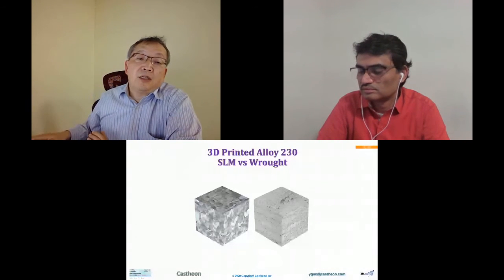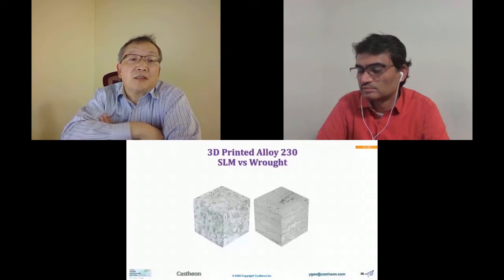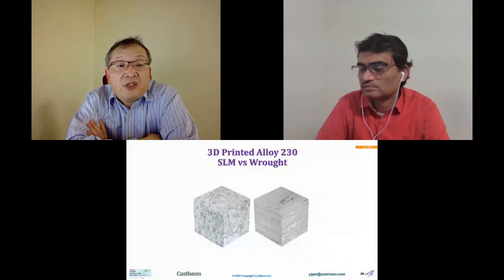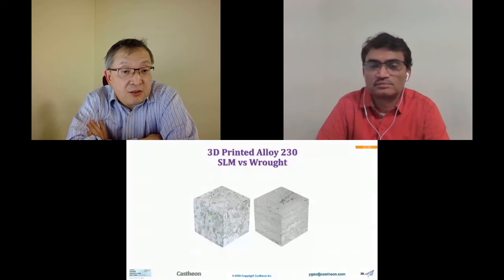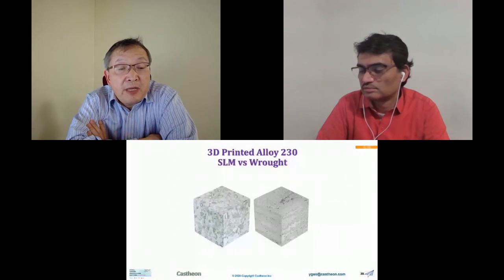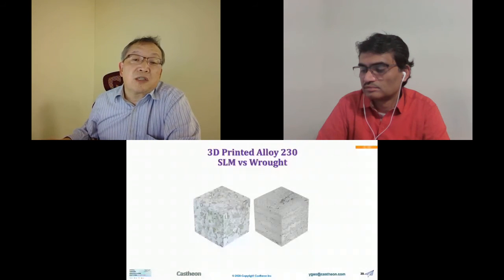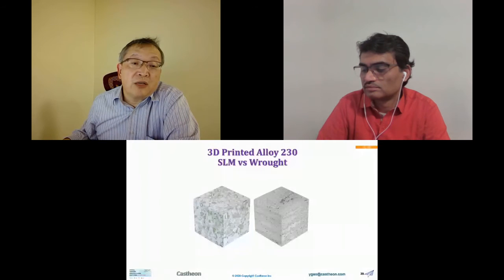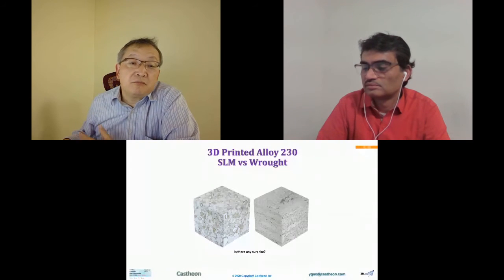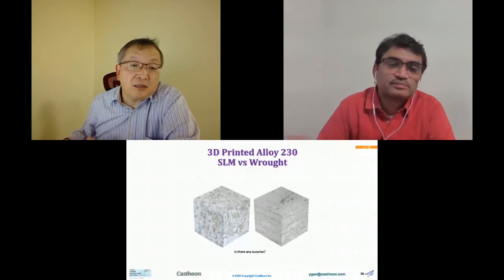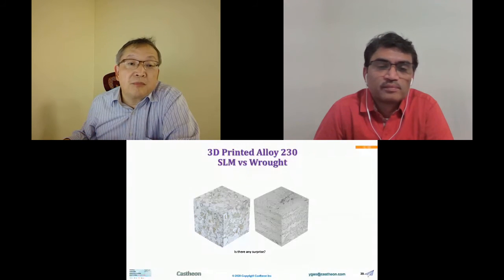But if you heat treat them, this is after heat treat, we were able to convert this 100%. Not all additive alloys can be converted 100%. There's a certain copper alloy that never converts. There's a certain aluminum alloy that never converts, and certain solid solution strengthened materials are very difficult to convert. So for most of the applications, we're converting them to have isotropic material properties. And on the additive side, you can see it's actually more homogenized than the raw material.